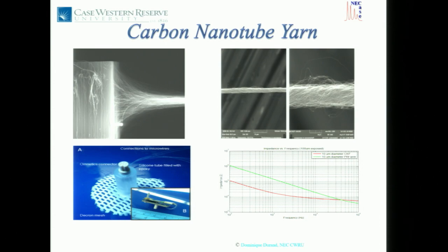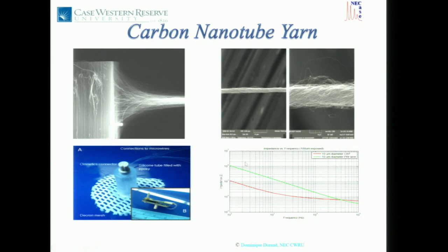Then you pull the corner a little bit and you twist it. So these carbon nanotubes, because of van der Waals forces, will bend down. So if I pull from the corner, it will bend down, and you keep following, you twist them, and you end up with a yarn, like this. And if you look at this in more detail, this yarn is made of individual nanotubes. Each one is about 500 micrometers long. So even though the nanotubes themselves are very stiff and very strong, the yarn is not, because it's made of all these individual nanotubes. But it's extremely flexible, and it has a huge surface area, of course. Therefore, it has a very low impedance. And if you look at this plot here, in red is the carbon nanotube impedance as a function of frequency, and in green is a platinum iridium wire with the same diameter, and you can see there's a factor of one order of magnitude lower.